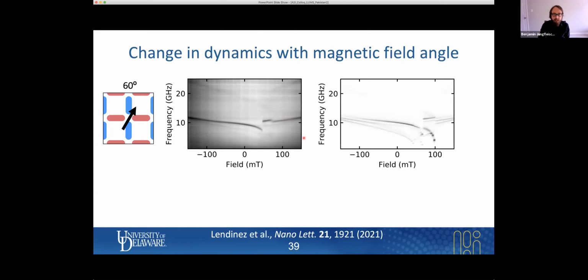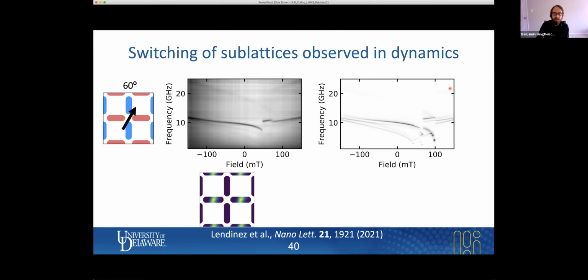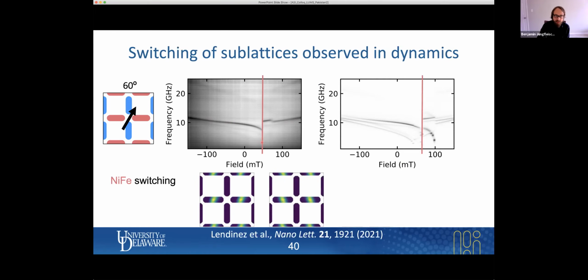Now, let me advance the slide so we see this also in the simulation, step up, step down, and this coincides with the switching of the NiFe (permalloy) that you can see here very nicely in the simulations. We can now also do space-resolved simulations. I'm showing here this mode. So we see that this mode is residing in the horizontal permalloy elements. And when the permalloy switches at this point here, this mode changes its tilt, as you can see here.